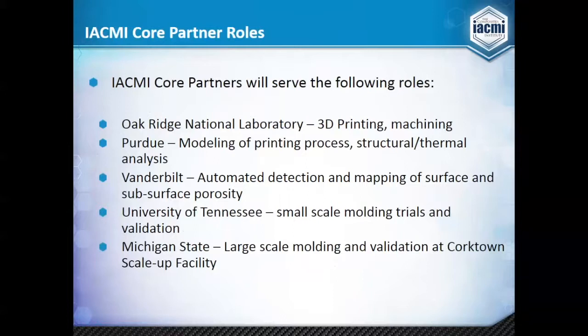Our friends at Vanderbilt, where most of our NDE work is headquartered. One of the things that you'll have in this, if you've dealt with a lot of cast parts, is that there's subsurface porosity that can occur. We expect there might be some in this case, but there is the ability to map the surface for porosity that can be seen visually or through some other NDE technique, but also maybe through thermography or other technology, to detect porosity that might exist a millimeter below the surface, that's going to give you a problem when you start to go into molding cycles and so forth. So we can map that and go in and fix those areas before the tool ever leaves the shop.